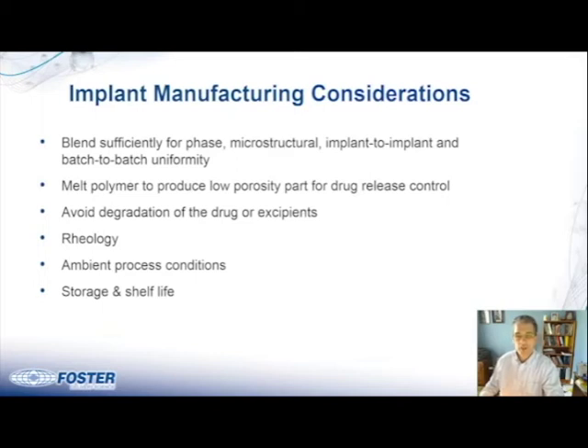It's critical to blend sufficiently for phase, microstructural, implant-to-implant, and batch-to-batch uniformity. It's also important to melt the polymer to produce a low porosity part for drug release control, and to avoid degradation of the drug or excipients. Rheology describes how the material flows in the process. It's important to understand the rheological characteristics of the formulation and how it influences mixing, and to obtain the melt strength required to form and shape the implant as it exits the extruder.